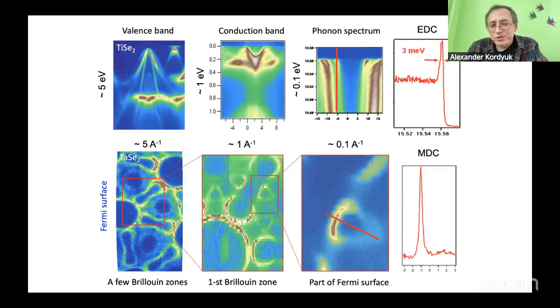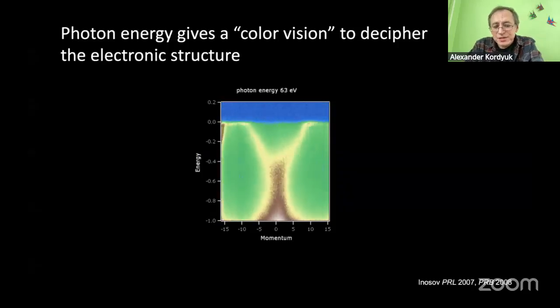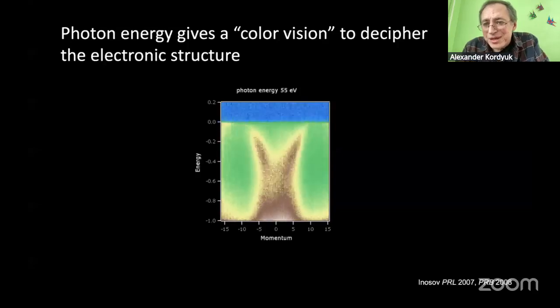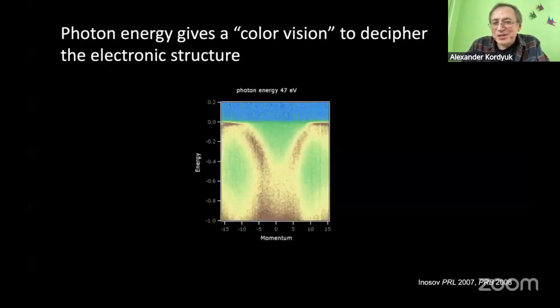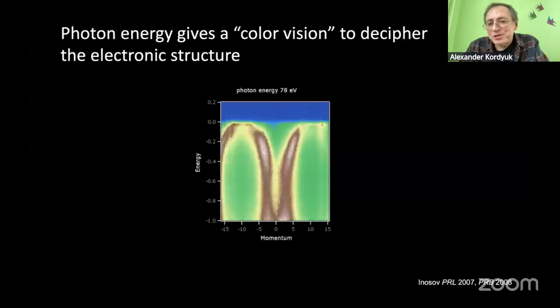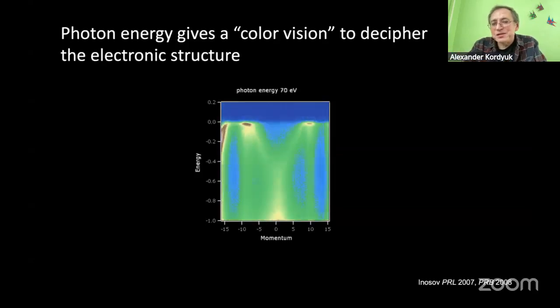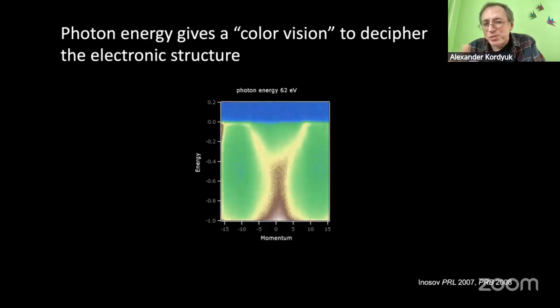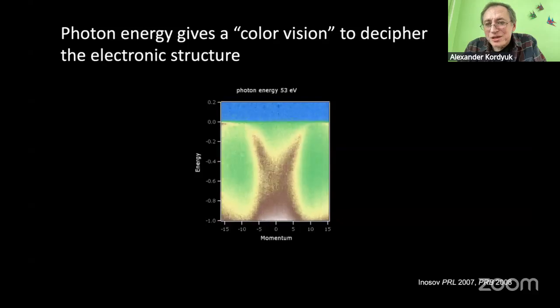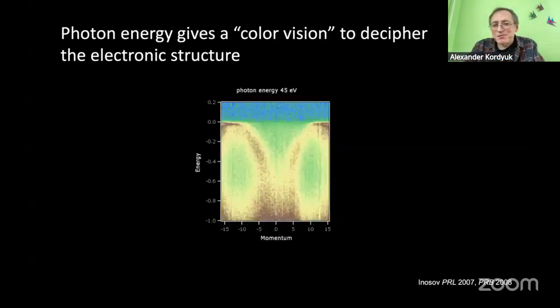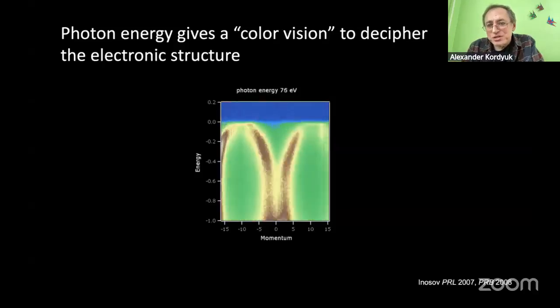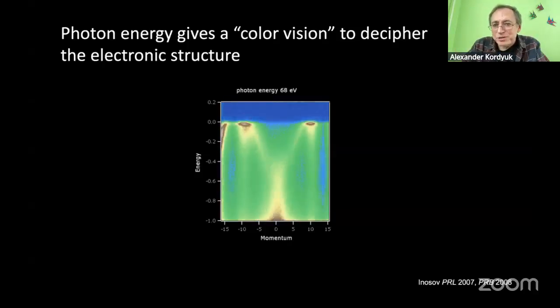To measure the whole valence band, you should have about 5 electron volts in depth. But to resolve fine structure like a superconducting gap and consequences of interaction, you need resolution down to milli-electron volts. The same is true for momentum space. I see that I will skip some information to say that the properties of the photons are also very important. In particular, it is exactly about your previous question: intensity is distributed differently, and when you change the energy or polarization of the photon, you change this matrix element first, and you can shine different light on different bands. The possibility to change the photon energy gives you something like color vision compared to black and white vision.